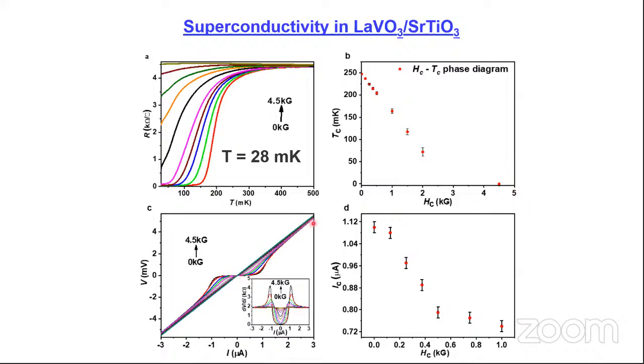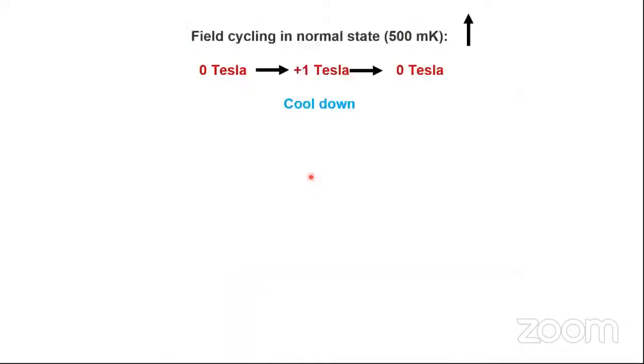Maybe what we have essentially are superconducting puddles that are percolatively connected with each other, because we can see that this zero resistance state is actually seen only at zero field and for very small values of current. So the features of critical current and the magnetic field dependence of that are clear. So from this, we conclude that this is a superconductor. And these measurements were done at 28 millikelvin. So this is the first set of results that we obtained from the dilution refrigerator that we installed recently.